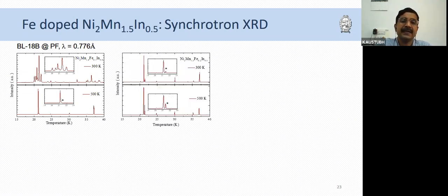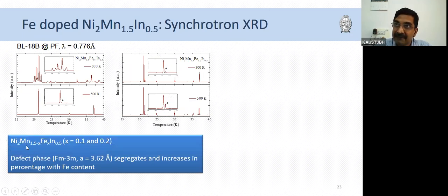7M modulated state. And we could also identify a small extra peak in this, which grew in concentration with increase in Fe content. So this is Fe 0.1, this is Fe 0.2, and you can see that this phase is growing. So what we can say is that in the MnFe series, there is a defect phase, which we could identify as a face-centered cubic phase with a lattice constant of about 3.62 angstrom. That is segregating and increases in percentage with increase in Fe content.